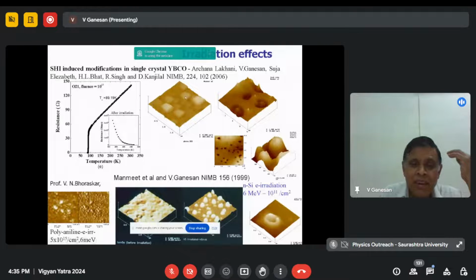And it's a very beautiful micron-sized golden biscuit structure. We see it in the color picture because we were so fascinated seeing this. And when you irradiate them, instead of getting a very good critical current, because every defect will act as a pinning center in a superconductor, those who work on superconductors know that, but then we could see a non-metallic conduction. We never understood it.